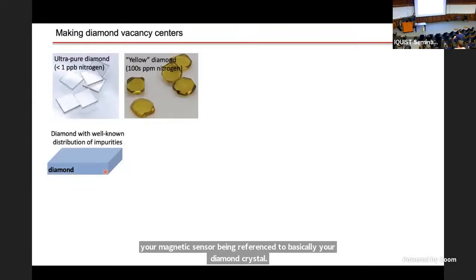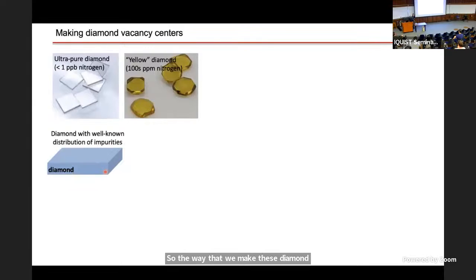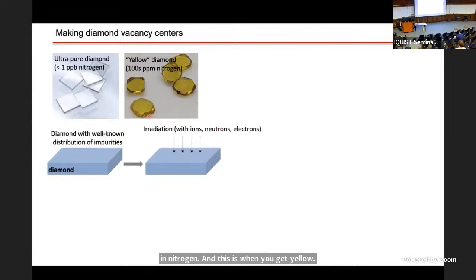The way that we make these diamond color sensors as a community could be done via growth, introducing these defects during growth, or it could be done after you have already grown the diamond, utilizing ion implantation. So you typically start with either very clean diamond, to the point where you have less than 1 part per billion nitrogen, or, as I've shown here, you can also start with diamond crystals that are intrinsically pretty rich in nitrogen, and this is when you get yellow diamond. And then you can send the sample out for implantation services.